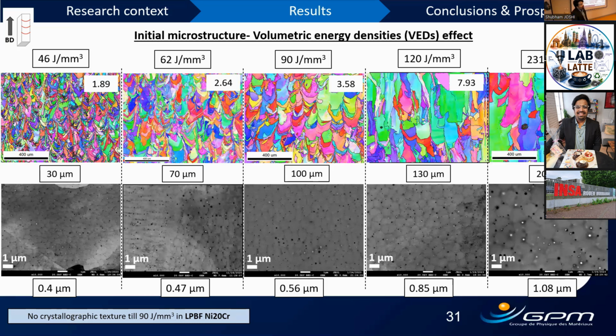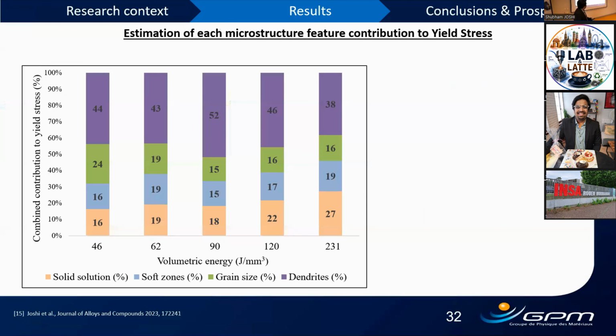So, well, yes, we should dig in first of all, and secondly, it is not of primary importance. Dendrites are still primary, and the contribution of grain size is quite significantly smaller when we compare it to the contribution of dendrites. So even if we have changes to the model, if it considers effective stress, effective grain size, I don't think it will supersede the dendritic contribution. So the model or the prediction will not change significantly by this understanding. But certainly to increase the accuracy, it is important to deep dive and to understand the aspect ratio, morphology, and, as you said, the effective barriers for dislocation movement or for backstress understanding indeed.